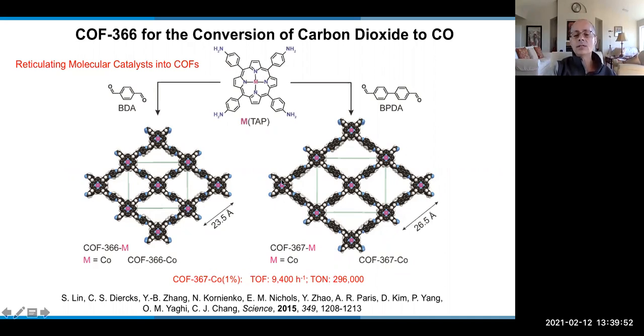But it turns out that because the catalyst is linked into a solid, the deactivation mechanism is blocked because now the molecules are farther away from each other and the active sites are exposed through the access from the pores. And so you get very nice turnover frequency and turnover numbers. So very nicely active material in the conversion of CO2 to CO.